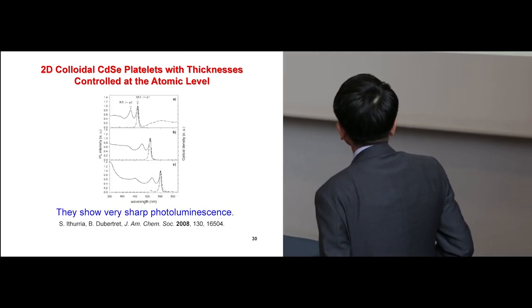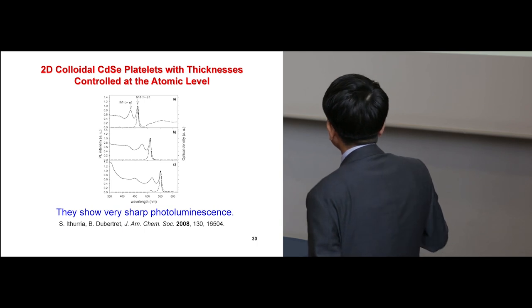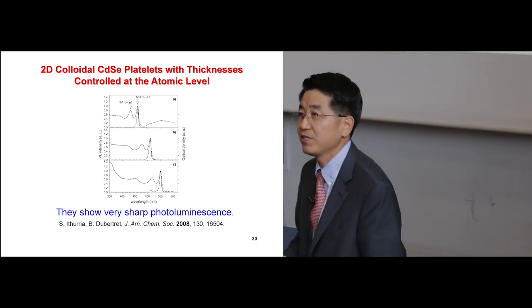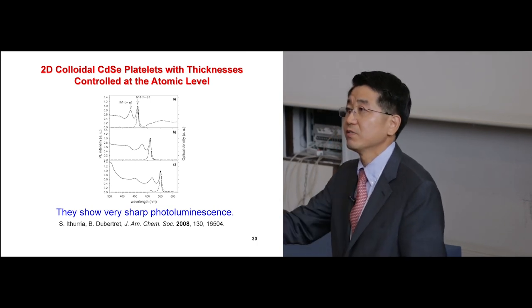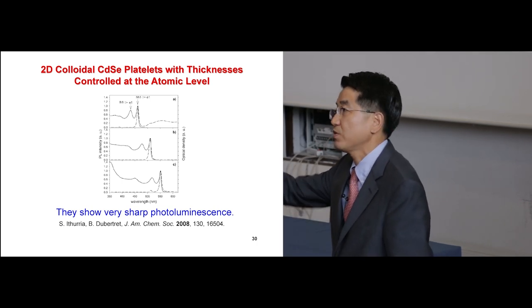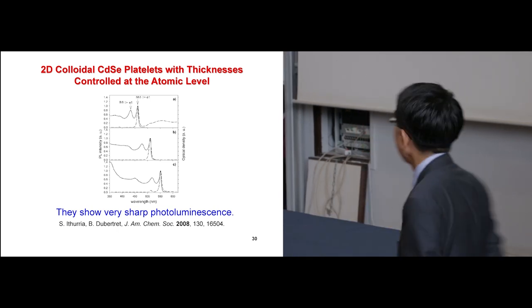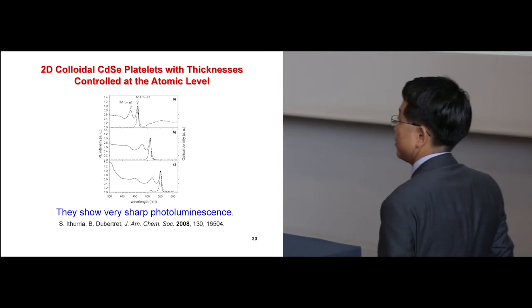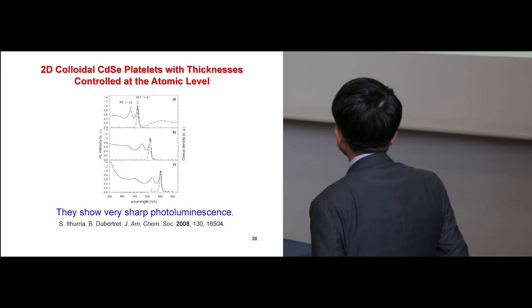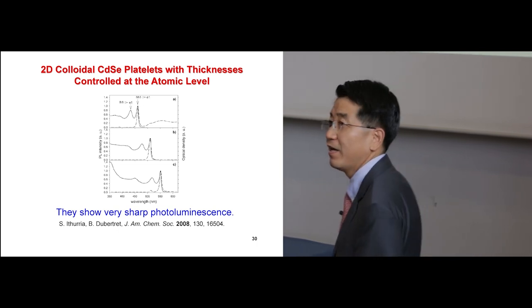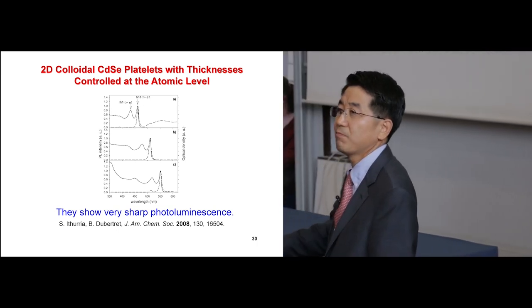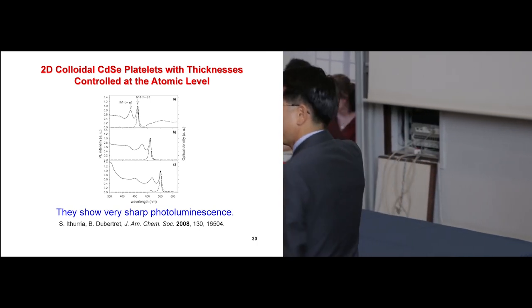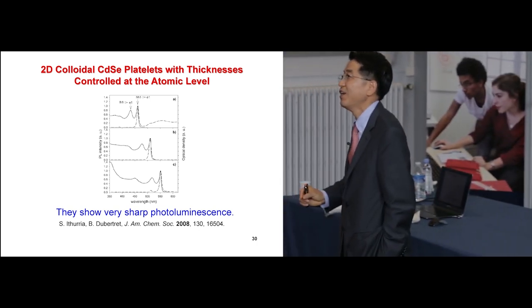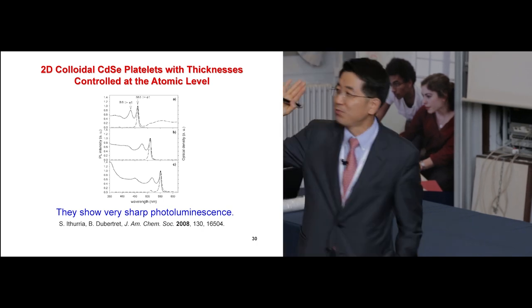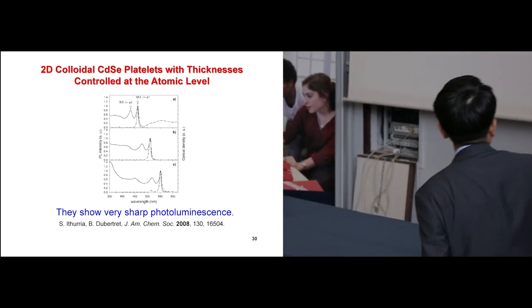And again, Benoit's group can also control the thickness, which is a really big advancement. We couldn't do it, actually. We were just stuck at 1.4 nanometer. And now he can control the thickness, as is shown here. It doesn't matter whether it is wurtzite or zinc blende structure. As long as you get thin quantum structures in the nanoplate, what you see is a beautiful, sharp PL, as is shown here.